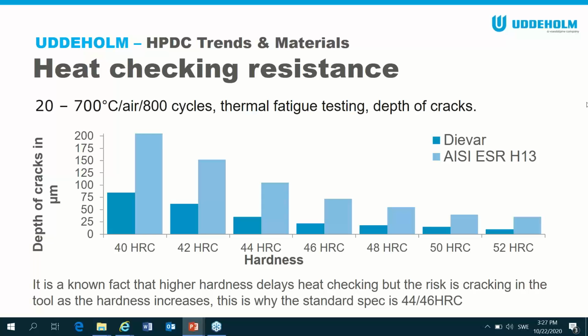And this is a really interesting chart. This shows you the heat checking resistance, how it goes up, even in H13. So you've got there 40 Rockwell to 52. And you see as the hardness of the material goes up in both Dievar, or in H13, the depth of crack decreases. So you can see on the right-hand side there, that's the depth of crack in microns.